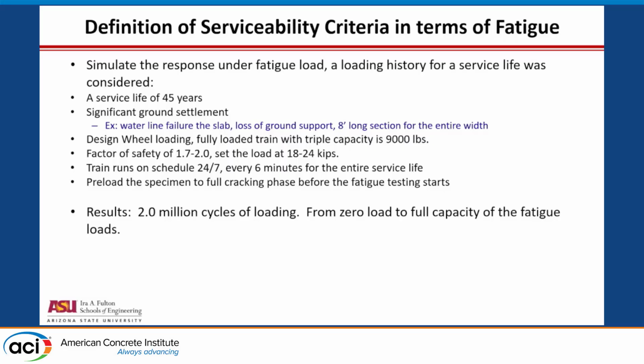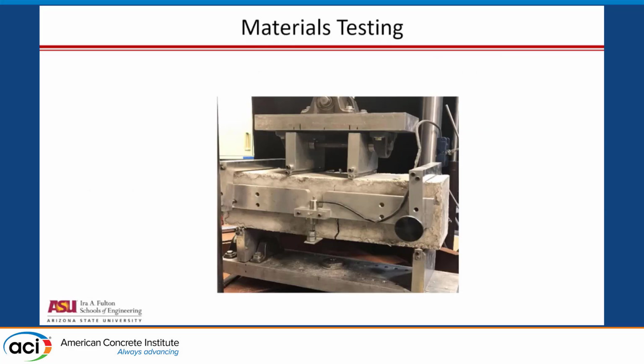Design for the wheel load, calculate the capacity per wheel, 9,000 pounds. Look at it as double with the factor of safety, so apply 18,000 pounds as a minimum load that the slab should take from the point of view of cracking. The train runs on a schedule of 24/7 every 6 minutes, so that ends up over a period of 45 years to about 2 million cycles of loading. And that became the criteria for our testing.